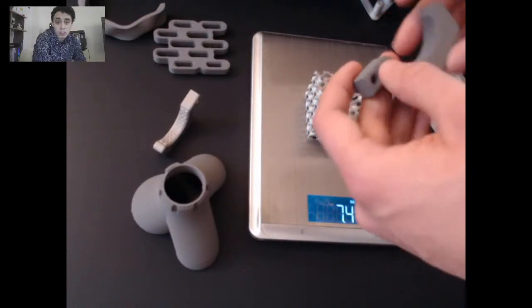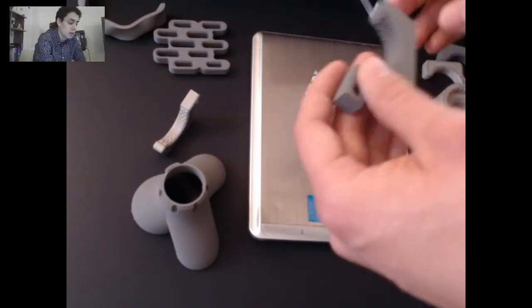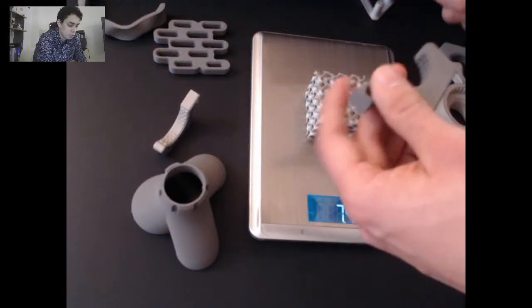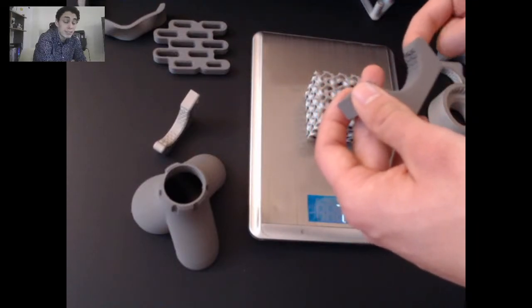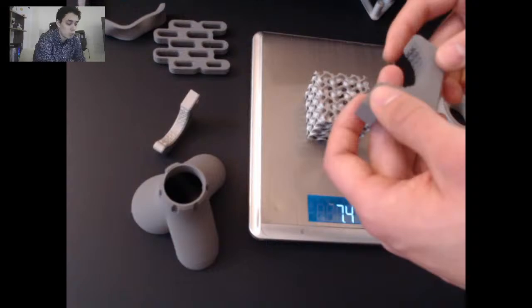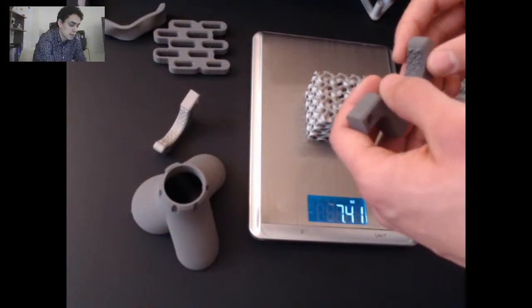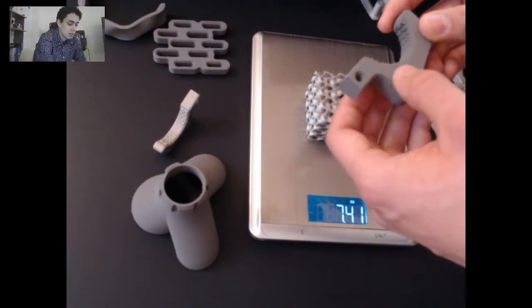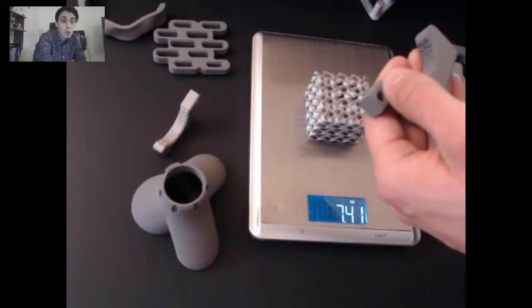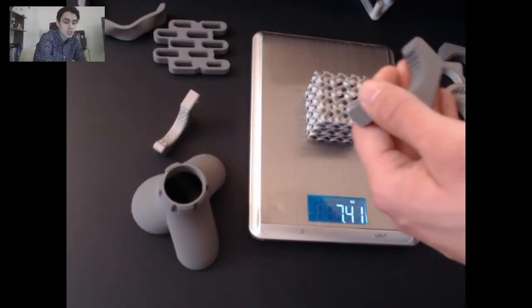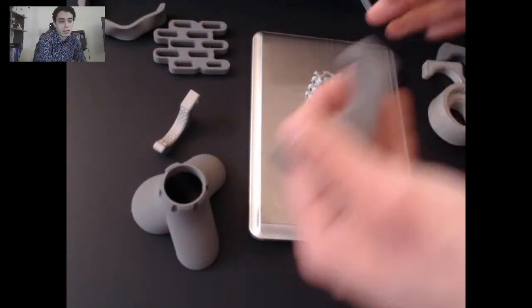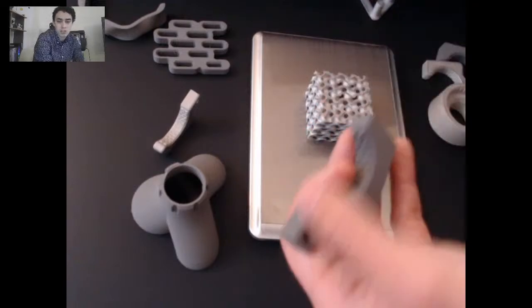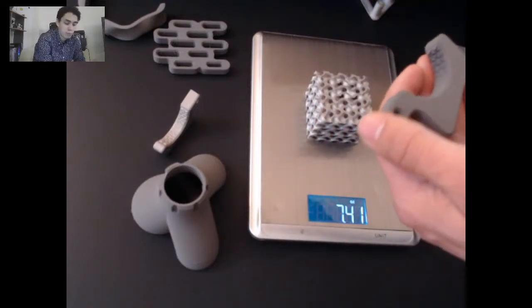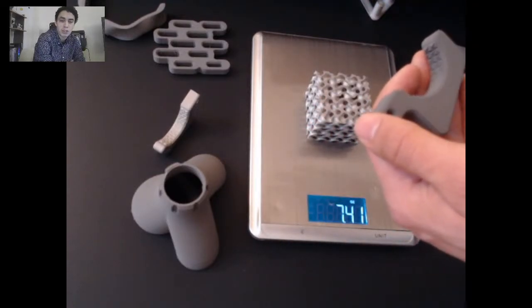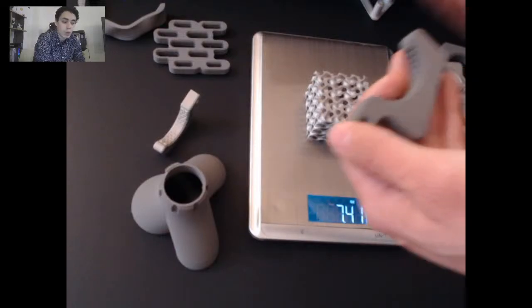What's the shrinkage percentage with this material? It's about 20% in X, 20% in Y, and 26% in Z. I was talking to BASF the other day, and the reason Z shrinks a little bit more is that the weight of the part itself will push some of the material down. In X and Y, you don't have the excess weight. There's no forces pushing from the sides. But in Z, you have that extra 6% due to the sheer weight of the part itself.